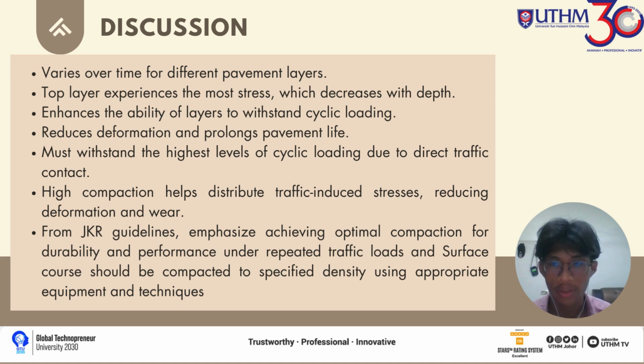Discussion for Figure 3: how stress varies over time in different pavement layers. The top layer experiences the most stress, which decreases with depth. Higher compaction enhances the ability of layers to withstand cyclic loading, reduces deformation, and prolongs pavement life. The surface layer must withstand the highest level of cyclic loading due to direct traffic contact. High compaction helps distribute traffic-induced stresses, reducing deformation and wear.